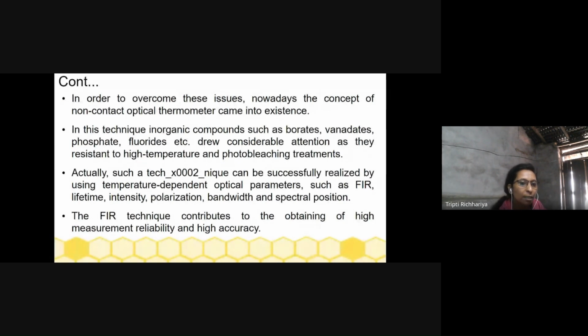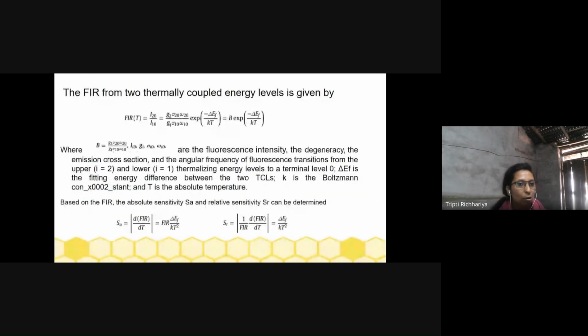An optical thermometer can be realized by using temperature dependent optical parameters such as fluorescence intensity ratio, lifetime, and so on. Of these techniques, the fluorescence intensity ratio technique contributes to obtaining high measurement accuracy. It is a very reliable and high accuracy technique. The fluorescence intensity ratio can be obtained between two thermally coupled energy levels with the help of this formula.